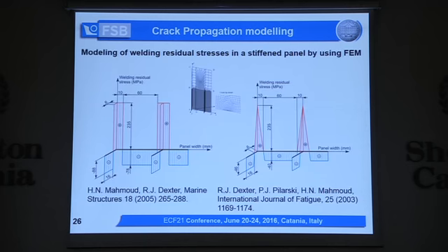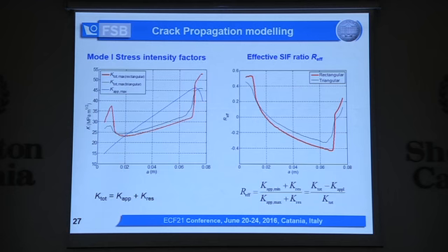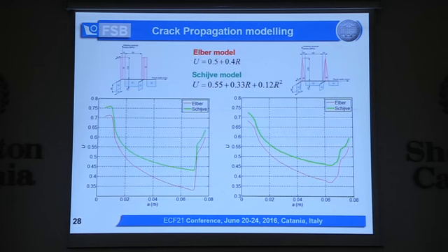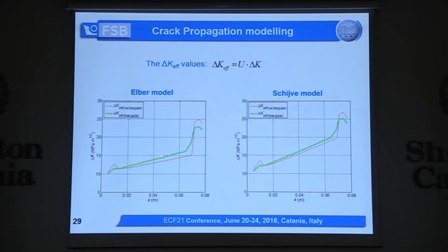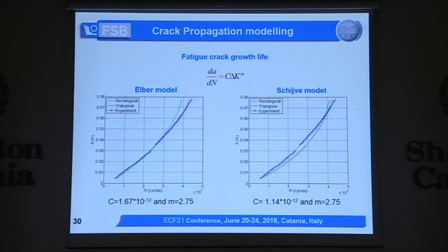So we consider some other distributions and other models to see what happened then. So two extreme cases are rectangular and triangular. And then we calculated the case again for rectangular and triangular. We need R effective for both cases. And then we need U functions, that's for Elber model and for Schijve model, and we plot them here. And finally we get K effective for rectangular and triangular, Elber model and Schijve model. And we again compared simulated life with experiment. So basically all these models give quite good agreement with the experiment, much better than without considering residual stresses, which would be something like this, what we have seen before.